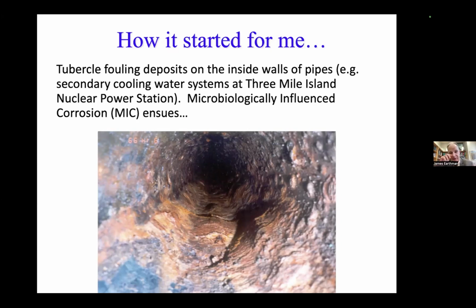This is actually after they tried to remove the tubercles during a routine shutdown of the plant. They took spheres with sandpaper on them. They flushed them through the system to knock the tubercles off. But that, as you can see, didn't really do much in terms of removing them.